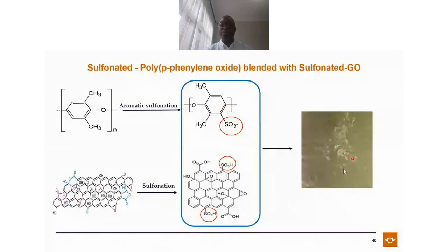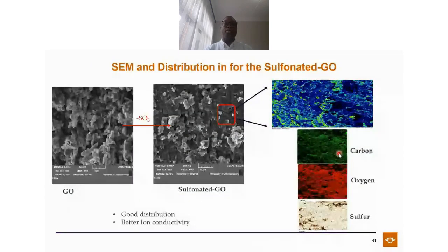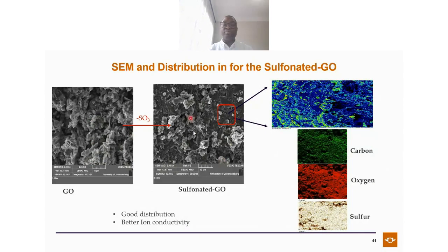This is the freestanding membrane that the student was able to obtain. You can see the surface is very smooth and it was very strong if you're looking at it with your naked eye. When you look at the SEM, we wanted to look at the distribution of this material. This is the normal graphene oxide, this is the sulfonated graphene oxide. Then we took a space here, we did what we call element mapping, and you can see that it's perfectly distributed. You're looking at the carbon, the oxygen, the sulfur within the material, it is perfectly distributed. That means you're going to have better ion conductivity.